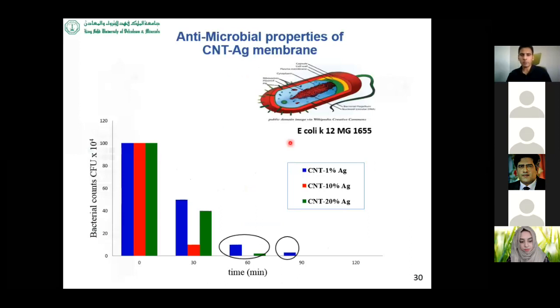We also perform some antibacterial study for this membrane, and we use E. coli as a model foulant, and we prepare basically a solution with specific concentration or colony forming unit of the E. coli or bacteria, and we pass those E. coli or those water through the membrane, and we found that membrane with various loading of silver were able to kill bacteria or remove the bacteria from water.